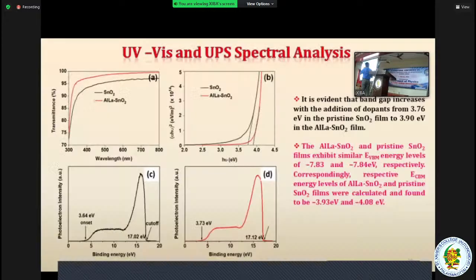That is the transmission spectra of pure tin oxide and aluminum lanthanum tin oxide. From this we can calculate the band gap energy. If we calculate it for pure tin oxide, that is 3.76 eV. That has been improved further to 3.9 for aluminum lanthanum co-doped tin oxide. Once you have the larger band gap, we can have more energy conversion.